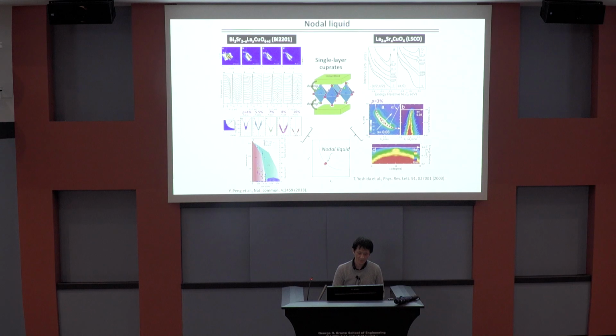In LSCO, the carrier doping level where the quasi-particle peak is observed can be much less, around 3%. But again, this peak appears only along the diagonal cut, or at a single point. If you go slightly off this point, the spectral peak immediately disappears and a gapped, dumped state appears.